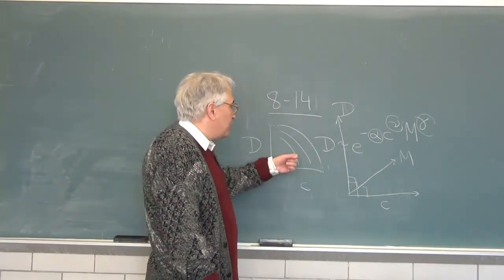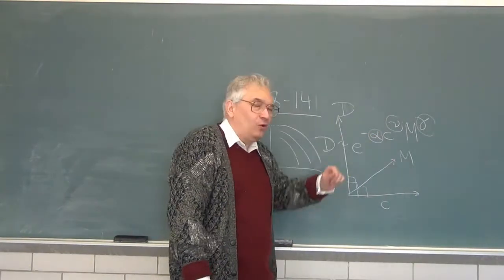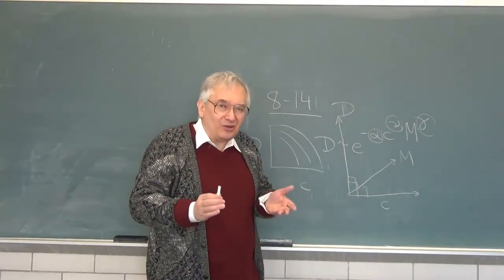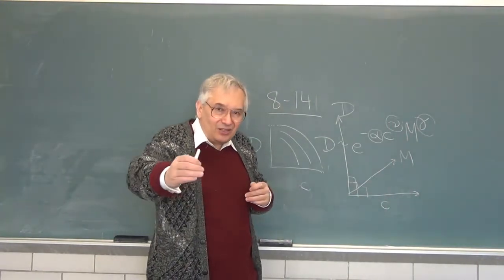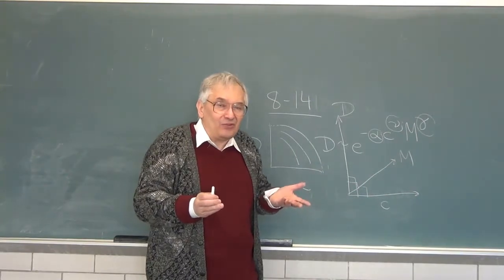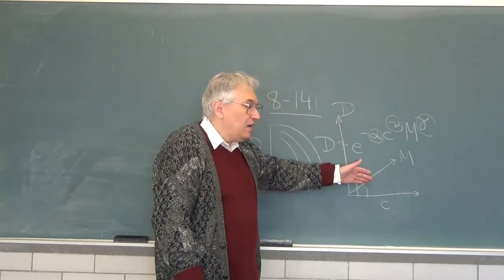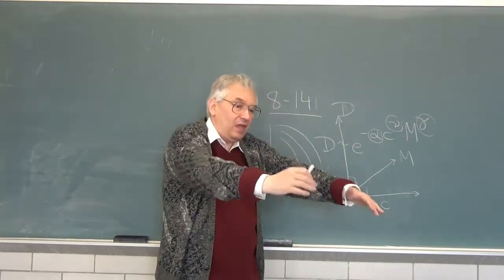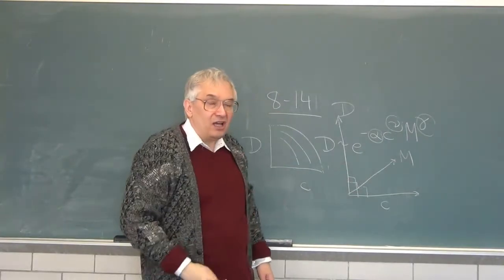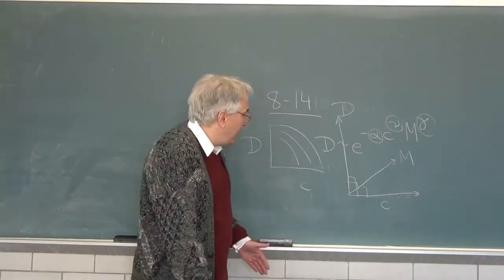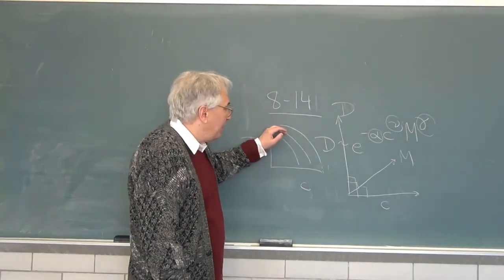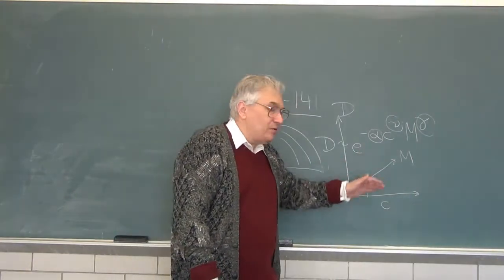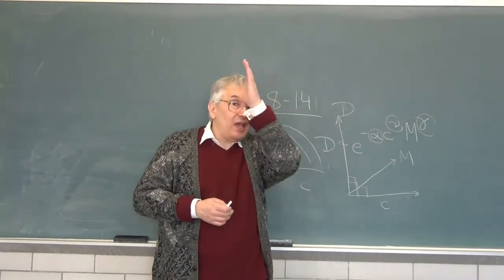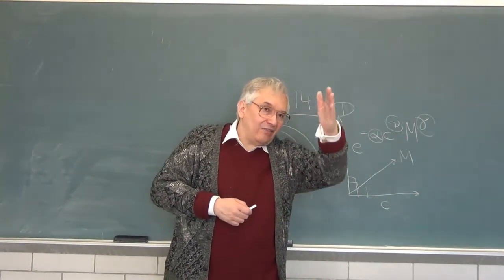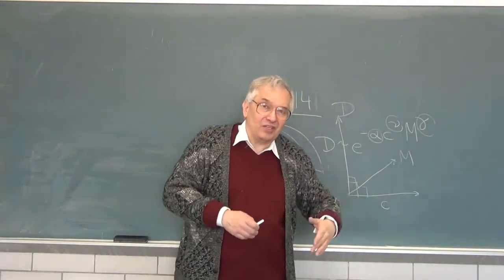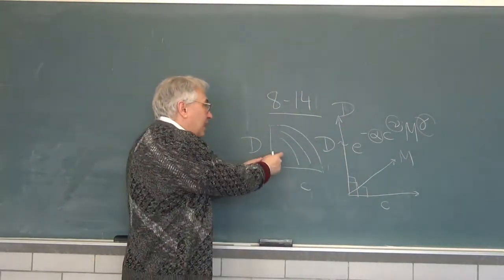When we do measurements for a set of fixed polymer molecular weights and a whole bunch of concentrations, remember, it's much easier to do measurements at a series of concentrations than at a series of polymer molecular weights. That's just the way the chemistry works out. When we do this, what we are doing is looking at this smooth surface and taking cuts at fixed constant polymer molecular weight. Each cut gives me a line, which is the shape of the surface at that value of M. So if the molecular weight axis is this way, I have a cut of the surface here, I have a cut of the surface here, I have a cut of the surface here. That's three lines, and I put the lines down on the graph.